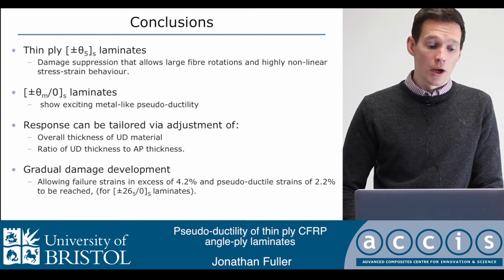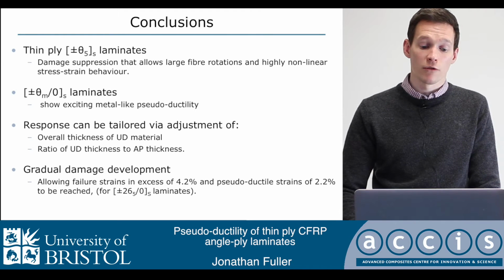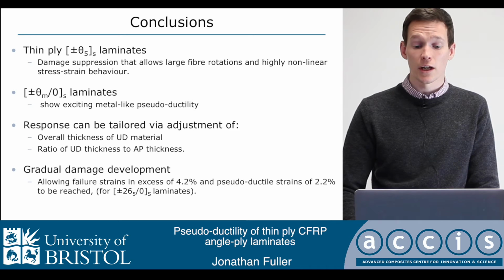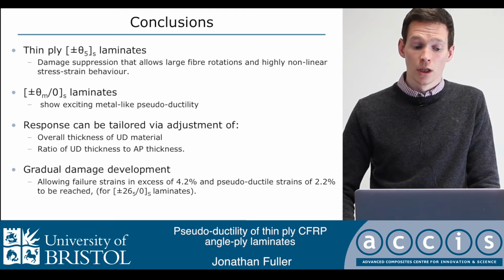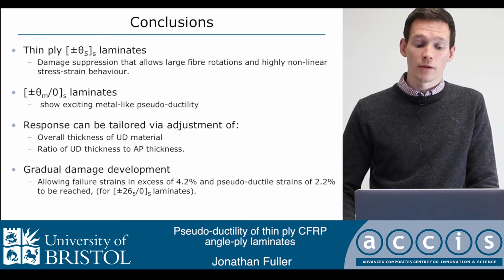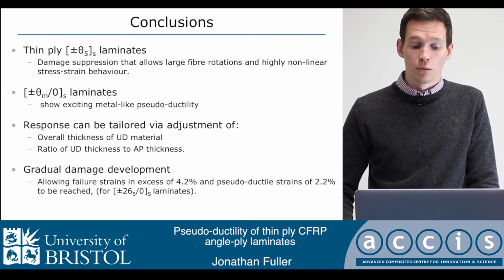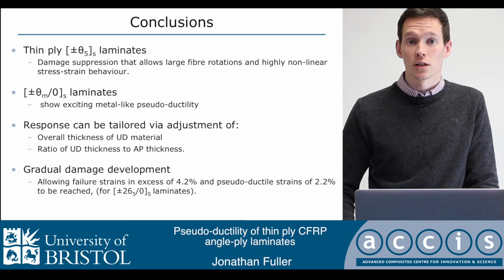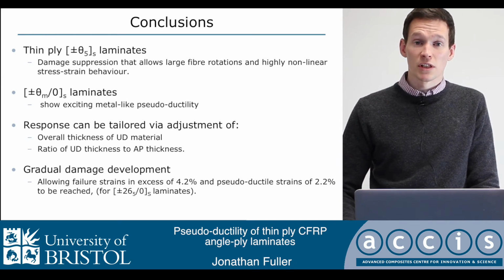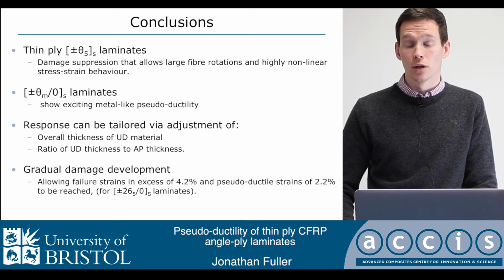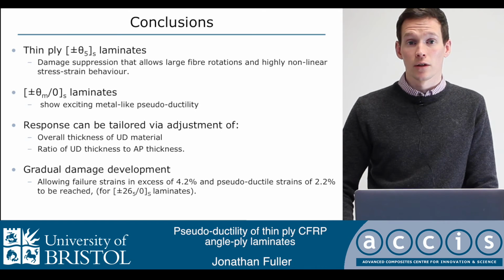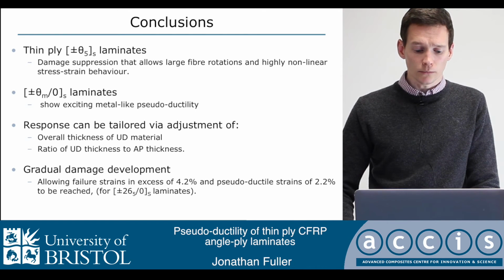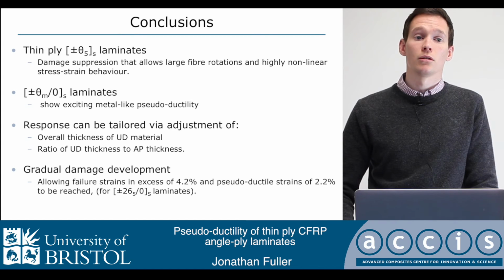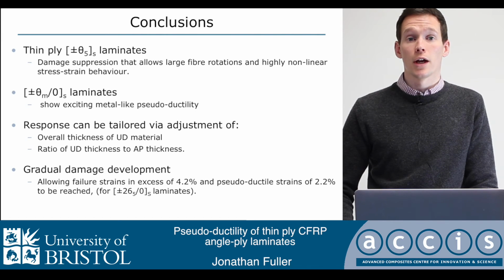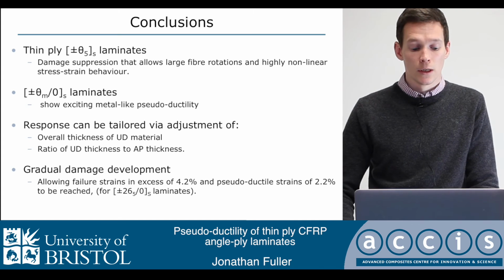So to conclude, we've managed to show that thin ply, angle ply laminates have suppressed damage until final failure, which allows large fibre rotations to occur and a highly nonlinear stress strain behaviour. Coupling that with a fragmenting 0 at the midplane, we've been able to show an exciting metal-like pseudo-ductile response, which can be tailored via the adjustment of the ratio between the angle ply and the 0 layers and the absolute thickness of the zeros. Most importantly, this allows us to have a laminate which displays a gradual development of damage rather than a catastrophic failure at the onset of damage.